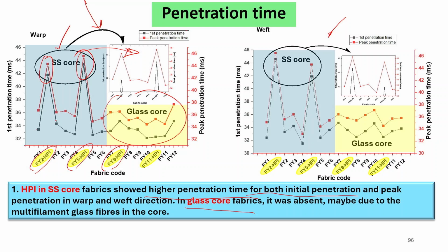This may be due to the multifilament glass fiber in the core, which may fracture quickly, and overall the penetration time is low in the case of glass.